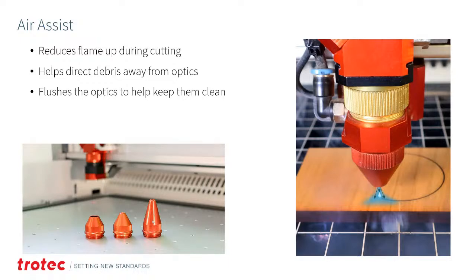If you do tend to have a material that has a lot of dust and debris and stuff like that, we have a lot of different nozzles that can be used with your air assist. The longer nozzles are used mainly for the 2.5-inch lens if you need to get the air down closer. We have a wide mouth cone and we have a narrow cone as well. The wide mouth is if you don't want a lot of directed airflow. Sometimes when I'm cutting materials like acrylic, if I direct it down the cut, it'll inject air into the molten plastic, and that molten plastic will actually form bubbles, and it can make the edge quality look poor. But if you cut it with a wide mouth cone, it broadens the airflow, and you get a much cleaner cut. Less of a chance of it blowing out flames, but it's also going to protect your optic.